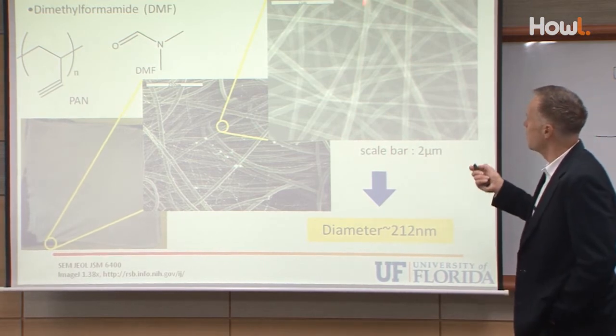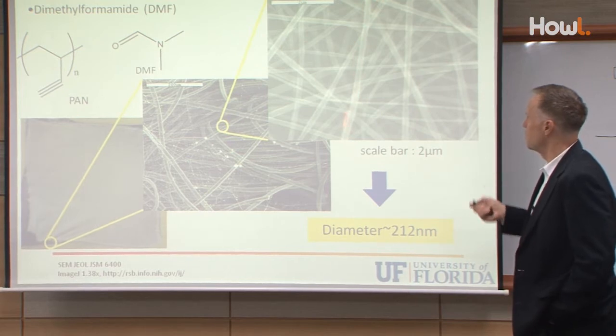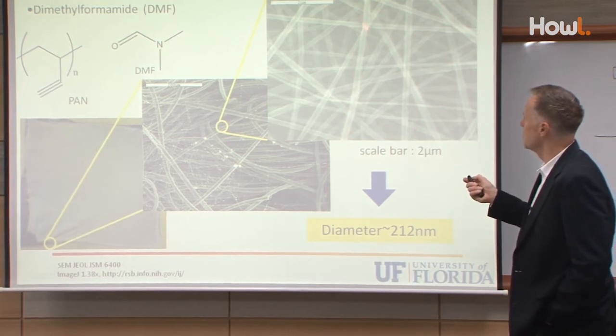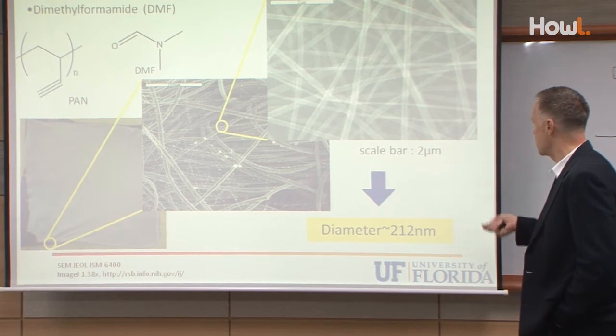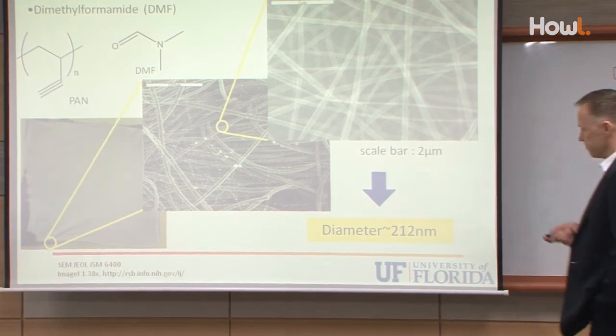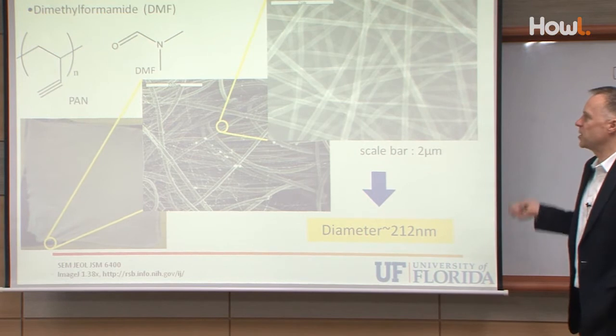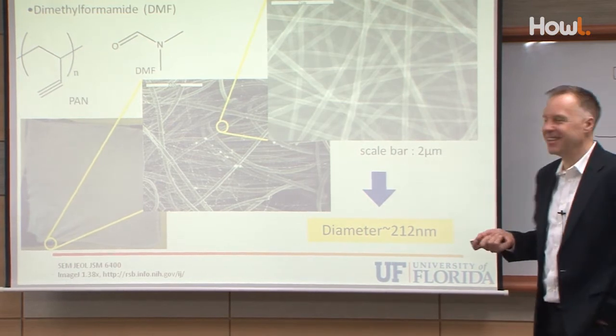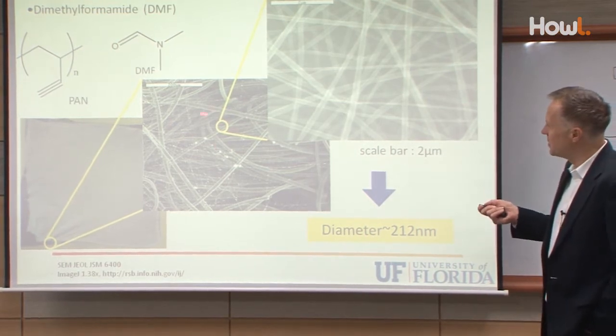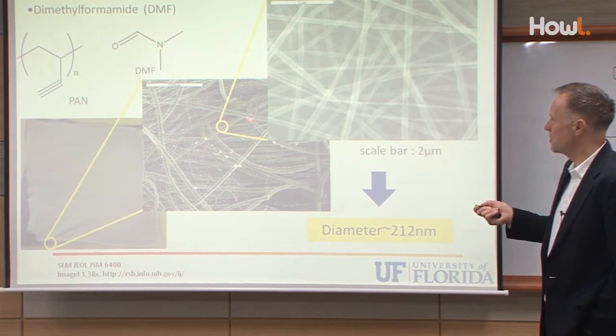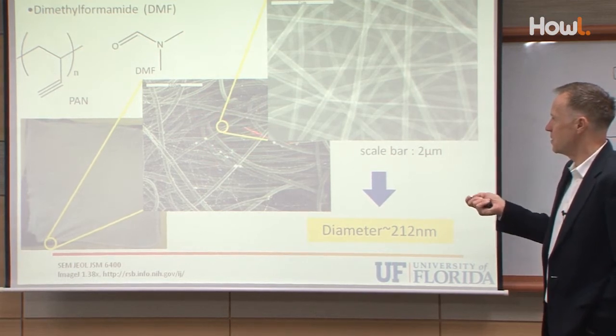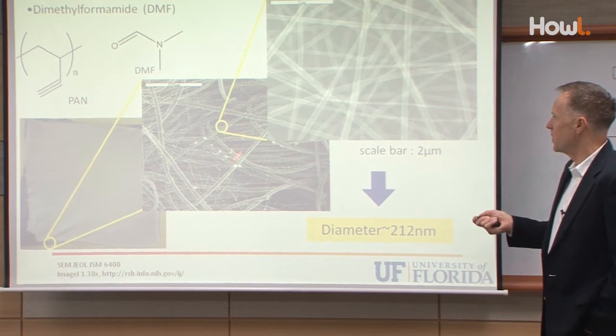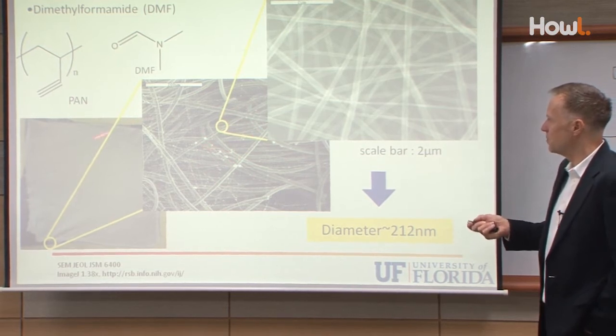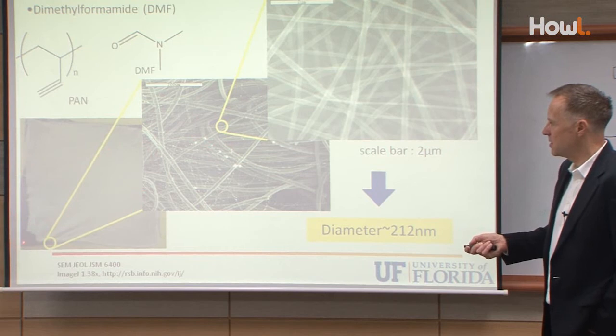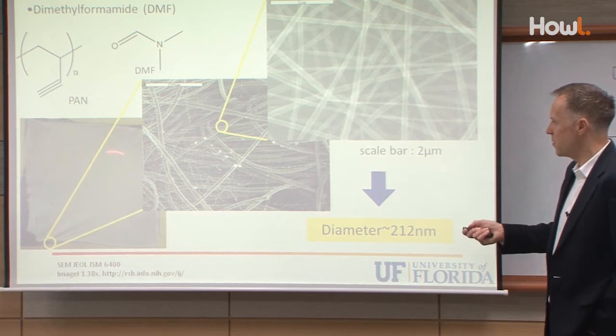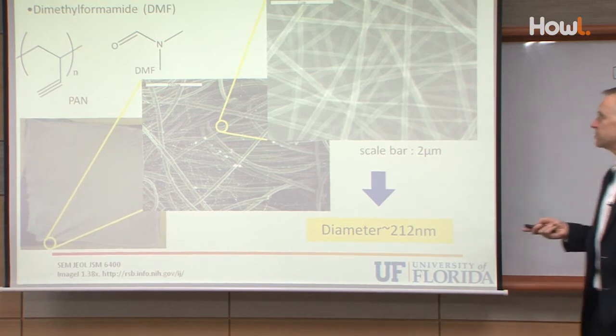So you see they're not just a few nanometers. This is 2 microns, so you're probably around 100 nanometers. Here it's actually 212 nanometers. So they're below 300 nanometers, which allows you to call them nano nowadays. And you see, of course, a big difference in dimensions compared to typical other fibers which are used as a support underneath. And yeah, here is now an entire fiber mat. So this is the support, and this is such a fiber mat. So these things can easily be formed.